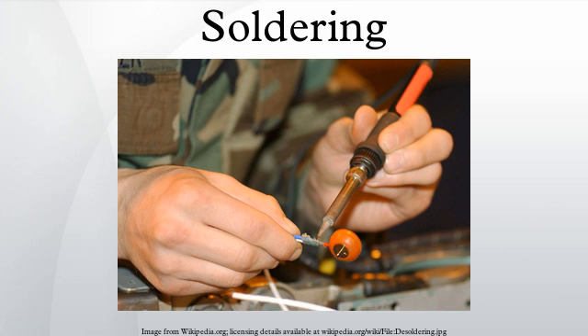When visually inspected, a good soldered joint will appear smooth and shiny, with the outline of the soldered wire clearly visible. A matte gray surface is a good indicator of a joint that was moved during soldering. Other solder defects can be detected visually as well. Too little solder will result in a dry and unreliable joint. Too much solder is not necessarily unsound, but tends to mean poor wetting. With some fluxes, flux residue remaining on the joint may need to be removed, using water, alcohol or other solvents compatible with the parts in question.